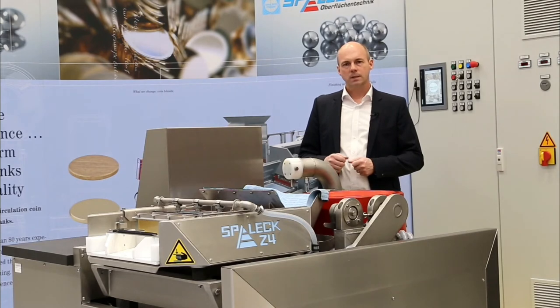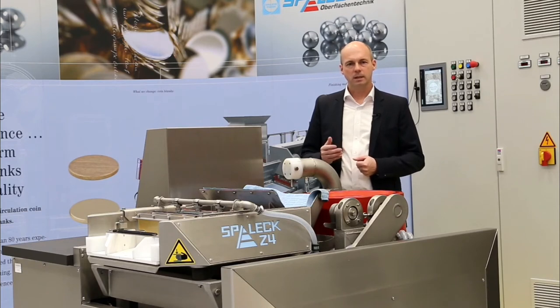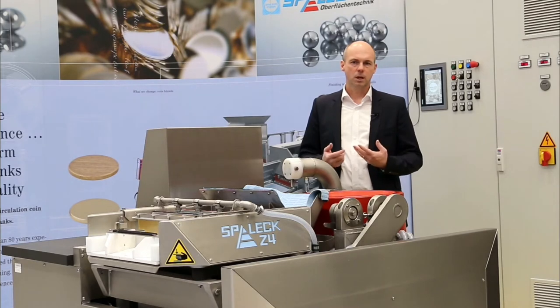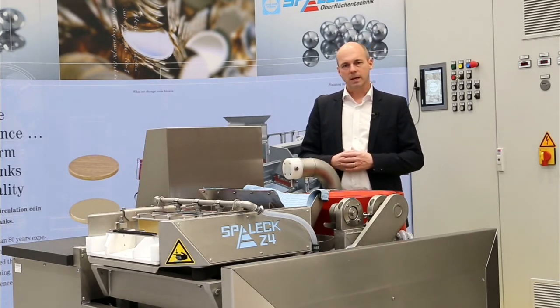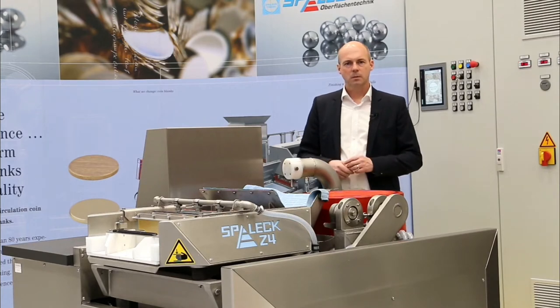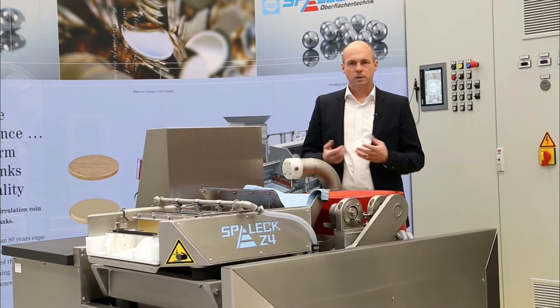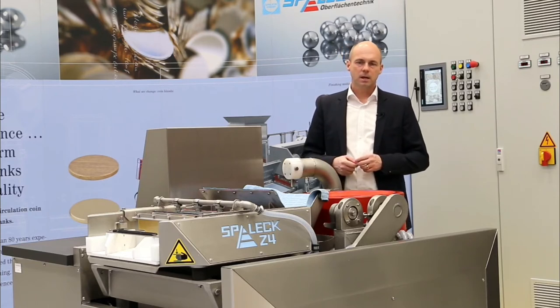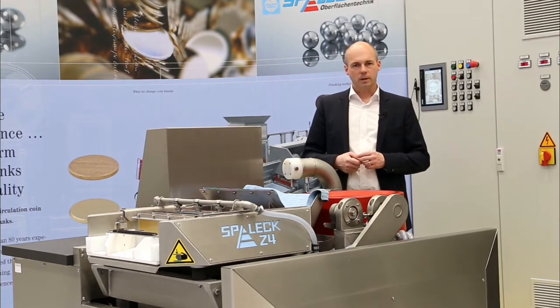We always started with a small pickling step, then went into the polishing phase, and finally applied rinsing to remove the residues from the compound before we separated the media from the blanks. The total process time was always 30 minutes. Afterwards, we dried them with a textile dryer and started to analyze the blank quality.